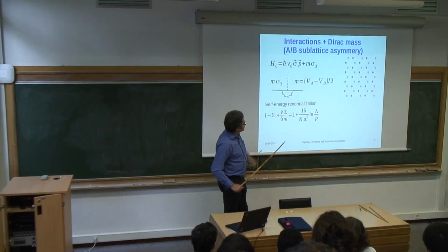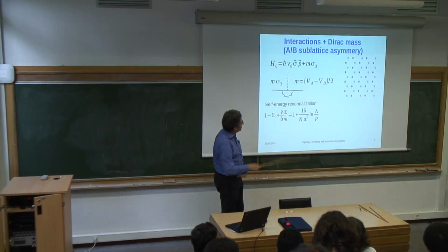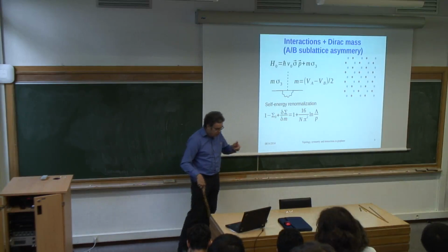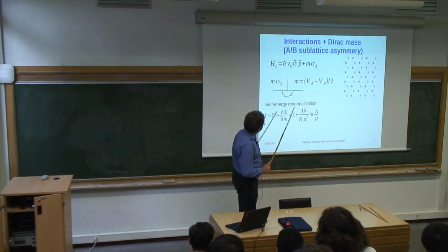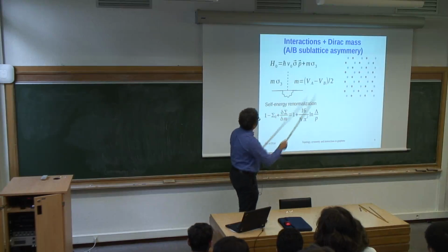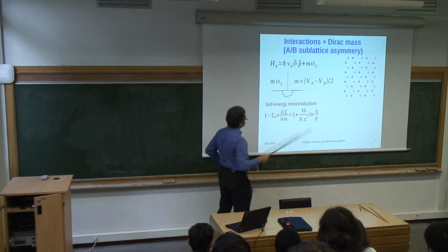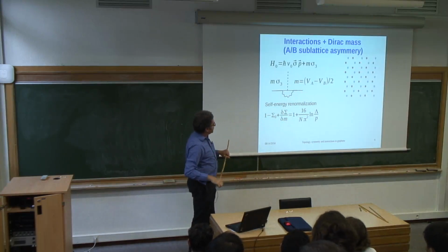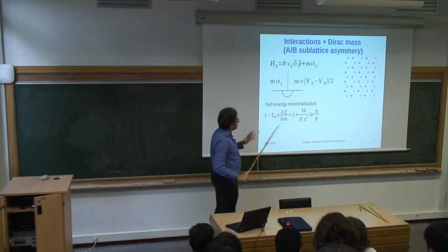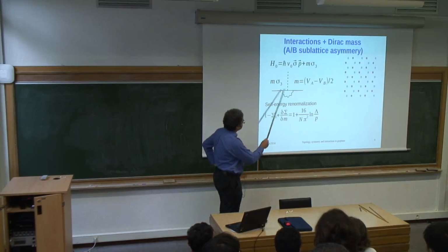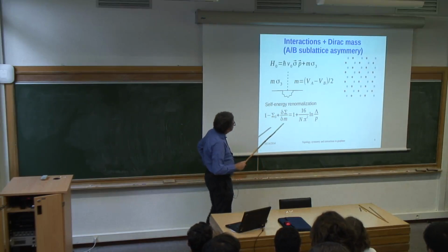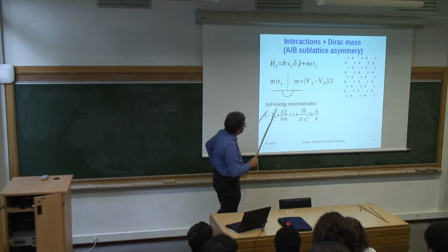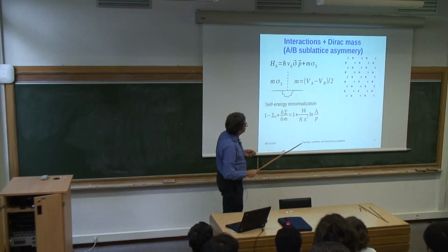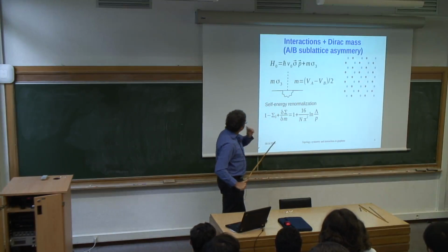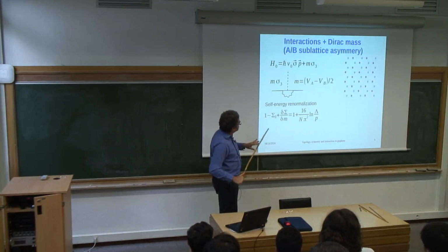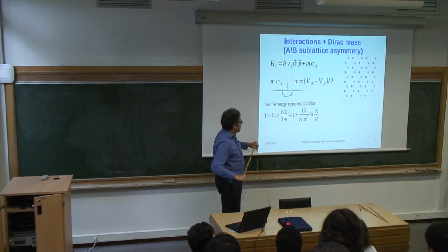If you introduce a perturbation that creates mass, let's say by putting on a substrate that breaks the A-B sublattice symmetry, you get gap opening in the Dirac spectrum, and you can describe it by a mass term. And then if you look at interaction corrections to that, there are log diverging corrections that arise from vertex corrections of this type, and you can ask how the bare mass that you have on the lattice scale flows under RG, and what it becomes at larger length scales,